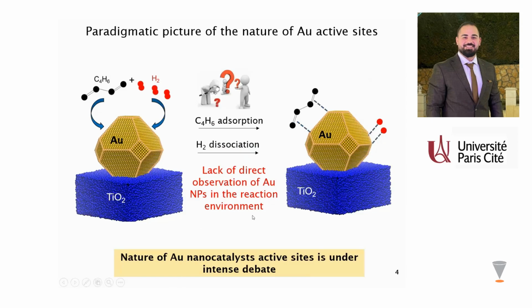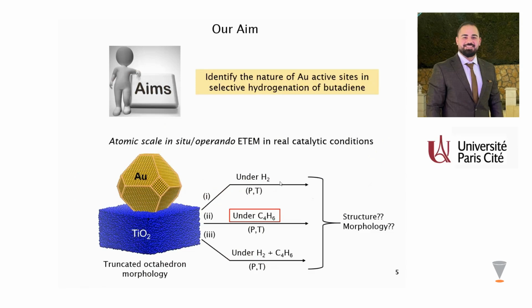So generally, the hydrogenation of butadiene to butene requires two processes: butadiene adsorption and hydrogen dissociation on gold nanoparticles. However, the nature of gold nanocatalysts' active sites during these two processes is under intense debate due to the lack of direct observation of these gold nanoparticles in the reaction environment and in real conditions. That's why our aim was to identify the nature of these gold active sites in the selective hydrogenation reaction by studying the structural dynamics of gold nanoparticles by atomic scale in situ and operando environmental transmission electron microscopy in real catalytic conditions. So the objective was first to study in situ the structural dynamics of gold nanoparticles separately under hydrogen and then under butadiene, which is the subject of the paper, and then to study in operando condition the structural dynamics of gold nanoparticles in the reactive mixture of hydrogen and butadiene.